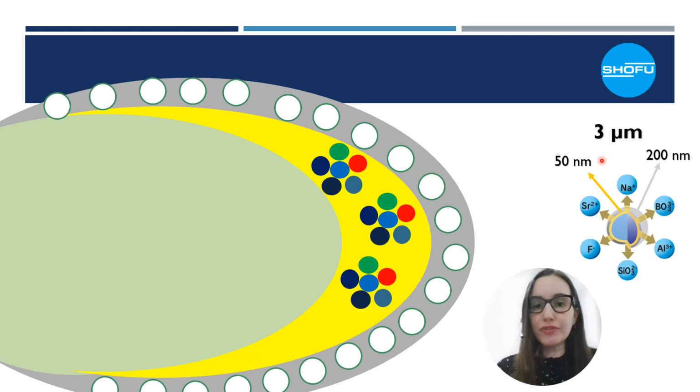So the SPRG filler is 60 times bigger than the glass ionomer layer. This layer is very, very thin, so that's the reason why the mechanical properties of the material are not compromised when we use this particle in the materials. And this one is responsible for the bioactivity of the materials.